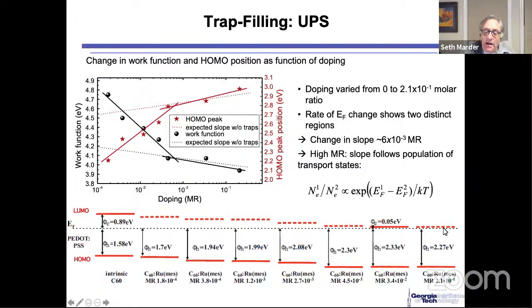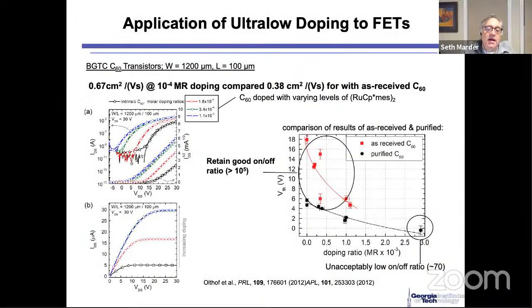Okay. And this was actually modeled by Jean-Luc Brédas. And an interesting thing, as I mentioned, is that first of all, you do see an increase in the conductivity, or in the mobility, when you dope C60. So let me show you, ignore all the stuff on the left of this slide. That's basically just the hard data from which the bottom line is extracted.